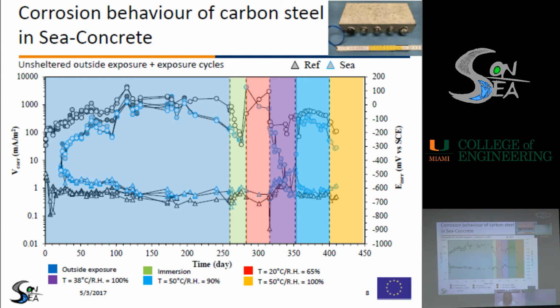This figure shows, as an example, the corrosion potential, which is presented by the circle symbol, and the corrosion rate, the triangular symbol, measured on the carbon steel bar embedded in the reference concrete, so in the concrete without chloride. Both the corrosion potential and the corrosion rate give an indication of the corrosion behavior of the steel. So when the corrosion potential is low and the corrosion rate is high, it means that the bar is active, so it is corroding. We can observe that during the first period of exposure in the unsheltered outside exposure, we had an increase of the corrosion potential and a decrease of corrosion rate, indicating the formation of the passive film.